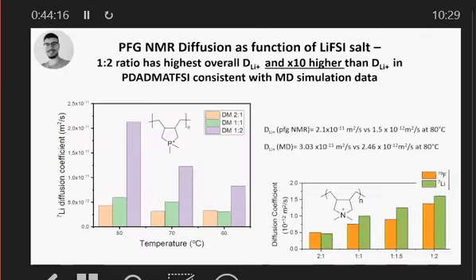Alex had come to Australia for some time last year and had a small amount of material with him, so measured diffusion coefficients of the system that he made, and all he had was the 1:2. We had 3 systems, 2:1, 1:1, and 1:2 materials with TFSI, FSI. And what he found then, which is really pleasing, when I went back to the data, is that the 1:2 system at 80 degrees, which is where the MD simulations are done, is about 2 times 10 to the minus 11. What do we measure in the MD? The MD is about 3 times 10 to the minus 11. So same order of magnitude.